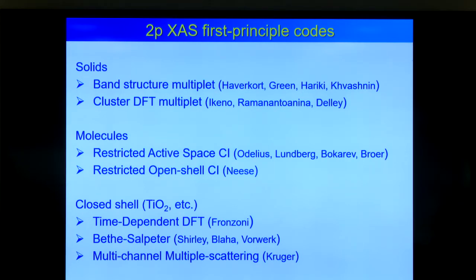So for the first two, it looked like you end up making a cluster in real space and then doing the calculation. Is there a rule of thumb how big a cluster should be for you to get a useful result? Yeah, in many cases, for X-ray absorption, a single metal is large enough for the cluster. So then it's a single metal and the oxides. Of course, they're not the most interesting systems. But if you have two metals, that can actually also be two metals in a protein, then of course it's much more interesting to do first principle calculations and do your fitting of your two metal sites.